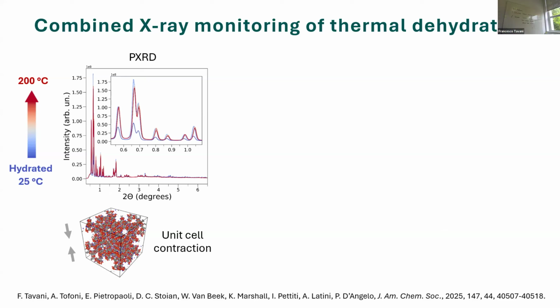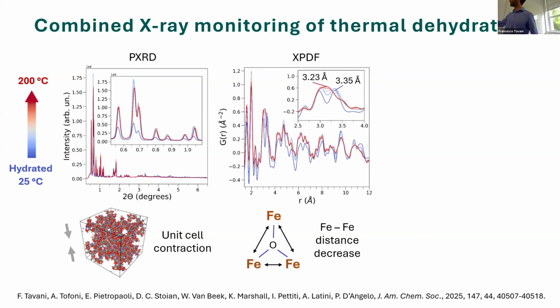These are the powder X-ray diffraction patterns going from the hydrated MOF, shown in blue, to the thermally dehydrated MOF in red. You can see there's a small shift of the peaks towards higher 2 theta degrees, and this is indicative of a slight unit cell contraction. If we look at the PDF data tracking the thermal dehydration, we see a double peak. One of the two peaks is located at 3.35 angstrom. These merge into a single peak at 3.23 angstrom, and this is due to a slight decrease in the iron-to-iron distance as water is removed from the MOF pores.